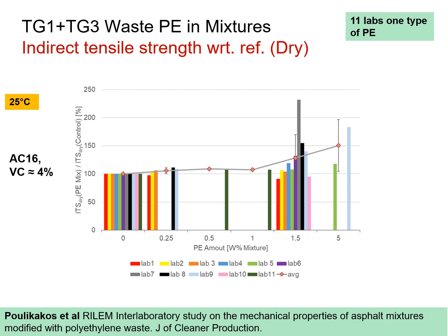TG3 and TG1 combined forces in looking at polyethylene blended with mixtures. In this case, an asphalt concrete with a maximum aggregate size of 16 millimeters was investigated using all local materials except for the plastic waste that was sent to them from Switzerland. This mixture also had a void content of about 4%.